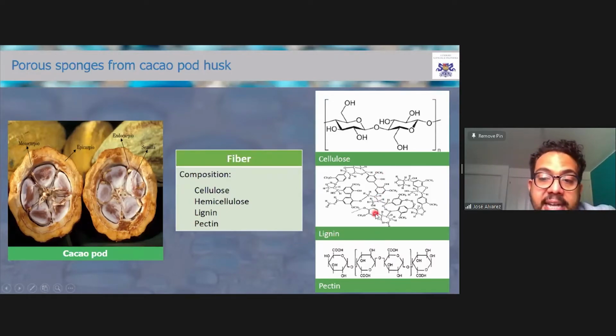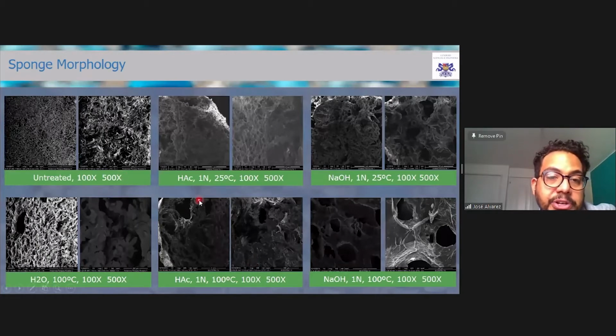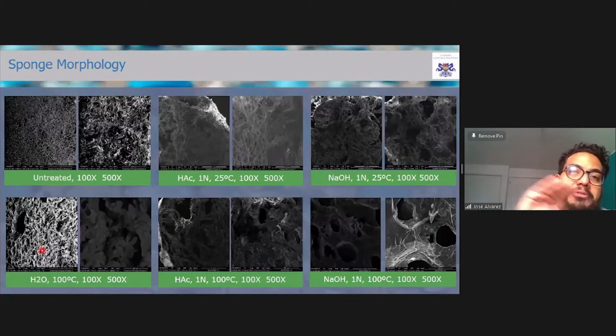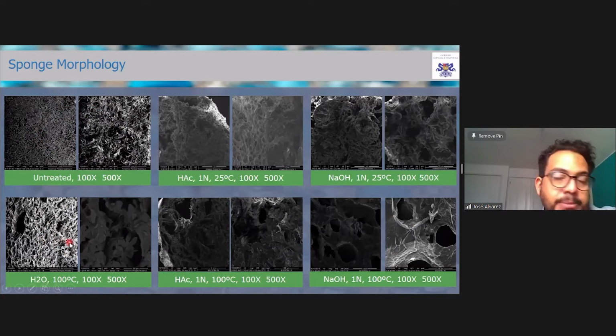So they're rich in cellulose and lignin and pectins, hemicellulose. And so we said, can we create porous structures from this material? And so we did different treatments. We did treatment with acetic acid, sodium hydroxide, only water, different conditions in temperature and time. And we were able to find these porous structures, especially with the acidic and the alkaline treatments. With water, we saw some porosity, but we demonstrated later that this was superficial porosity. It wasn't internal porosity.